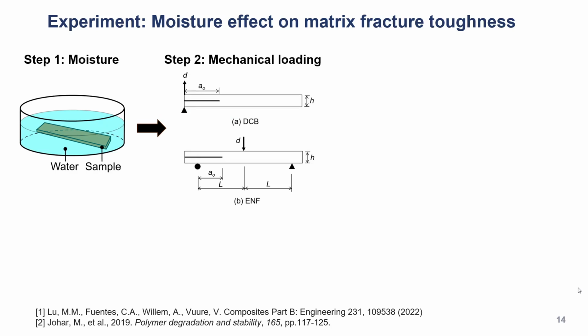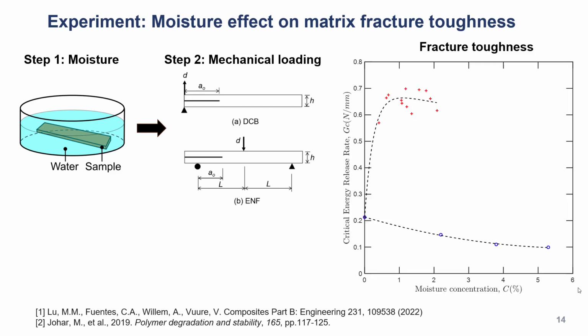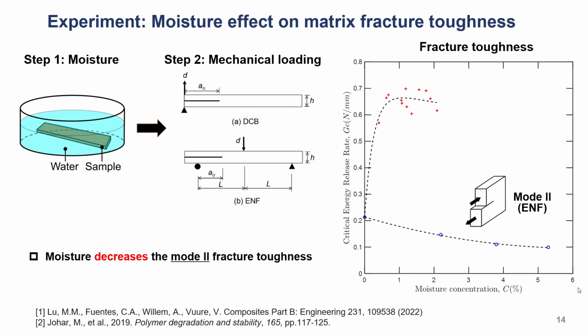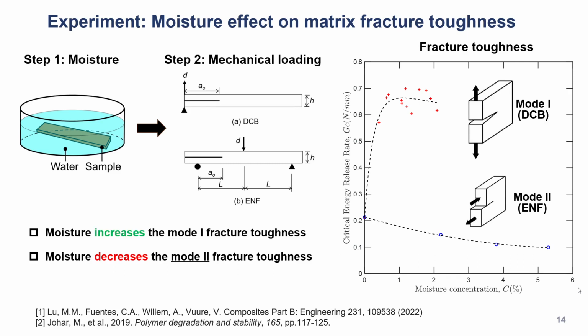In experiments, people tend to age a sample in water for a few days, and then take it out and do the mechanical loading. You can quantify the mode 1 and mode 2 fracture toughness. As you can see in this graph, it plots the fracture toughness against the moisture content. Surprisingly, you can see the moisture decreased the mode 2 fracture toughness, but at the same time, moisture can increase the mode 1 fracture toughness. So why is that? What are the mechanisms here?